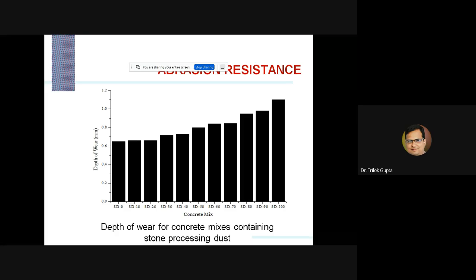Now it comes to the abrasion resistance, and this figure shows the abrasion resistance in terms of the depth of wear. So in this case, up to 20% only, the values are similar as compared to the control mix. Beyond that, the depth of wear is increasing, meaning abrasion resistance is decreasing.